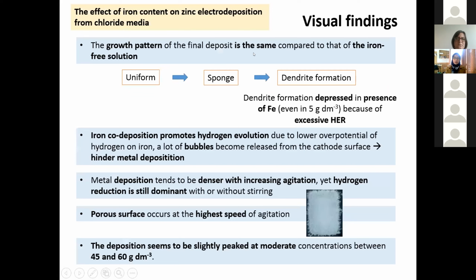And then what happens if the iron is there? When the iron is there, the pattern is still the same, but we can see that there is some decrease of the dendrites. So our resulting deposit is actually good as a visual appearance. But if we look closer, we can see that a porous surface has formed there.